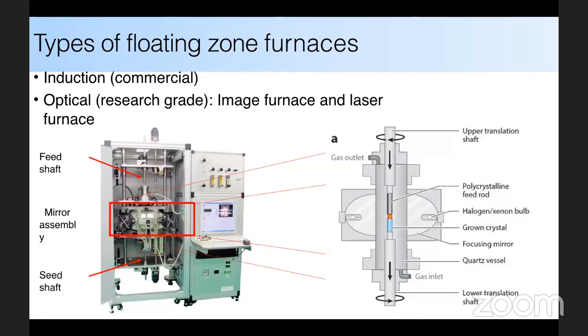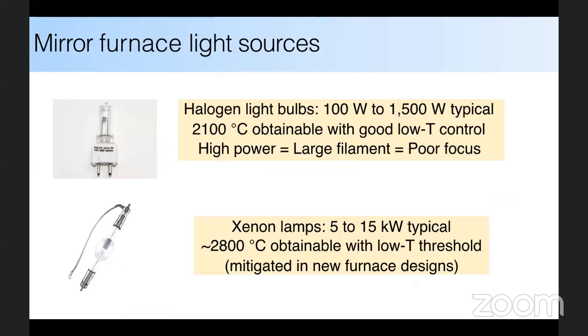You can see here at the bottom is a seed rod, and top is a feed rod. And once they start going down, you can get very nice crystals. So in this optical float zone, people use a halogen lamp sometimes, sometimes a xenon lamp, which can give a temperature around 2100. Recently, people even grow crystals at 3500 degrees Celsius.